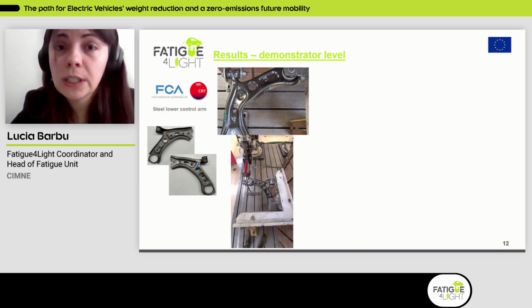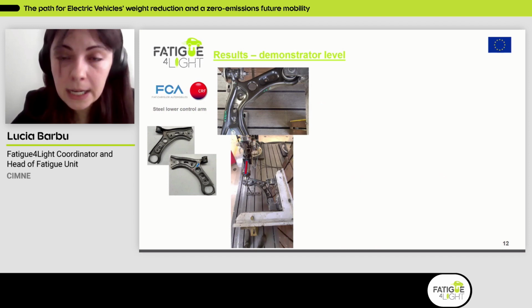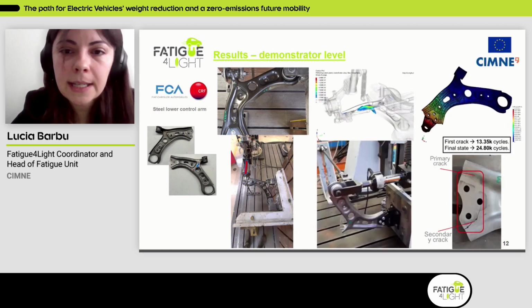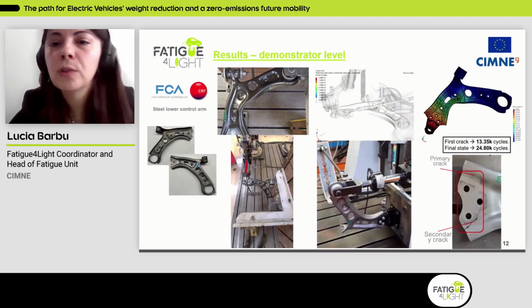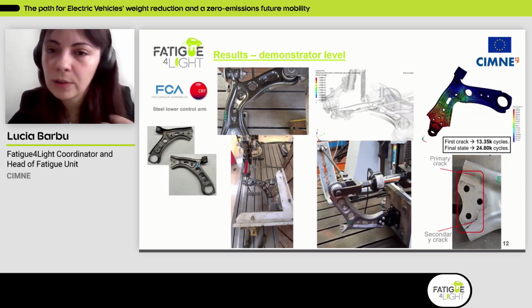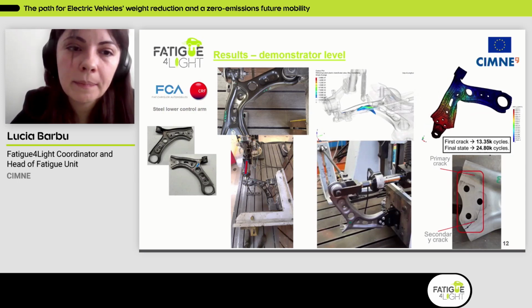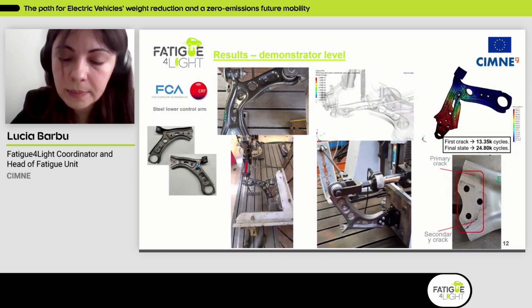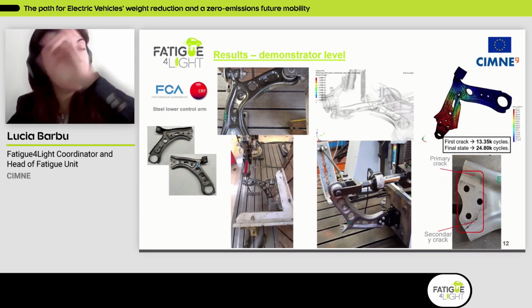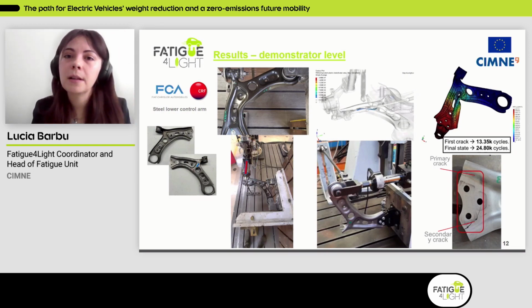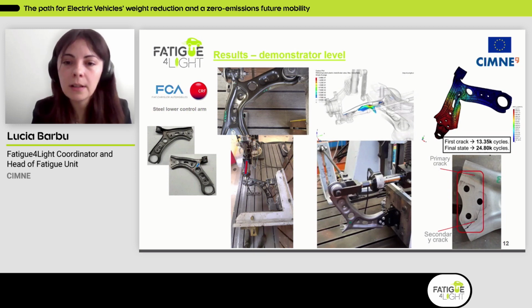First, of course, a monotonic test, so a misuse test. And you can see here, for instance, the failed specimen under this misuse test. Also, from the numerical simulation part, we also tried to give an answer to these different types of behaviors that were observed experimentally. And after that, we passed, of course, to the fatigue test. And there were several fatigue tests that were done on this component.